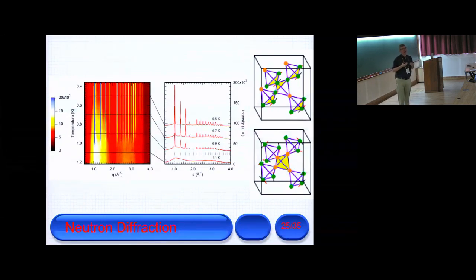So in a nice system, one wave vector will define the whole crystal structure. Sometimes you need two, so you have two wave vectors to define it. In the pyrochlores, you can have many more. So here I show a 1K structure and a 4K structure. And you have 2K structures, 3K structures. And they all show exactly the same Bragg peaks. If you just calculate it, they're exactly the same. So from a powder average system, you can't distinguish them.